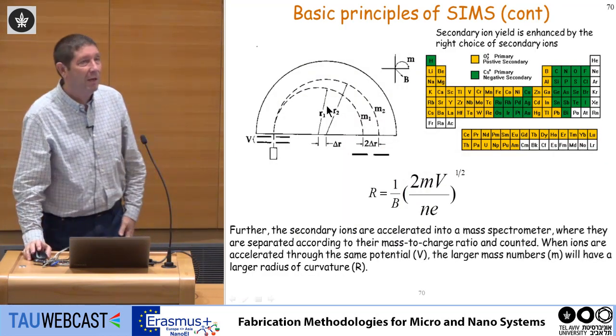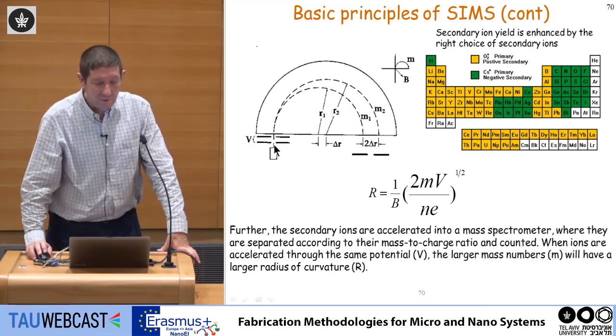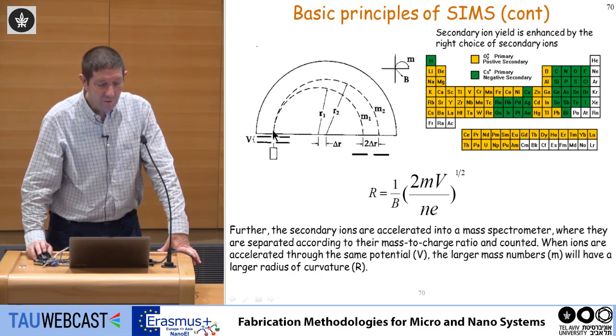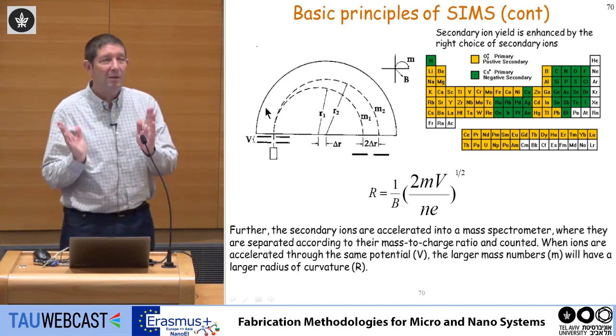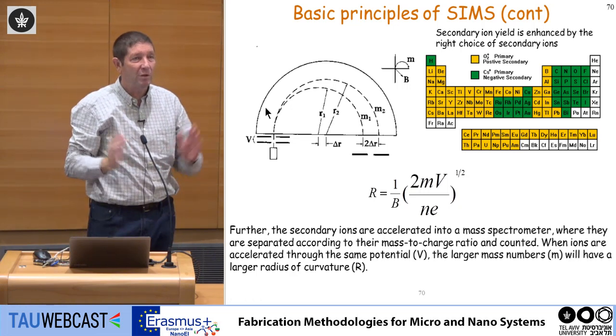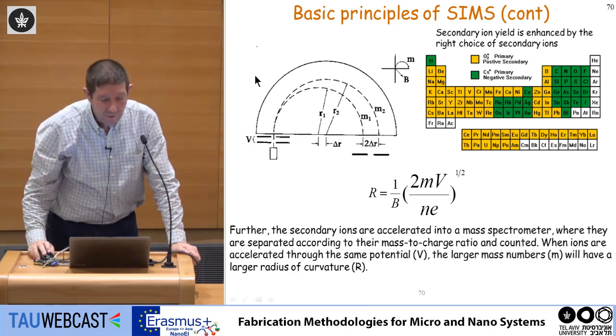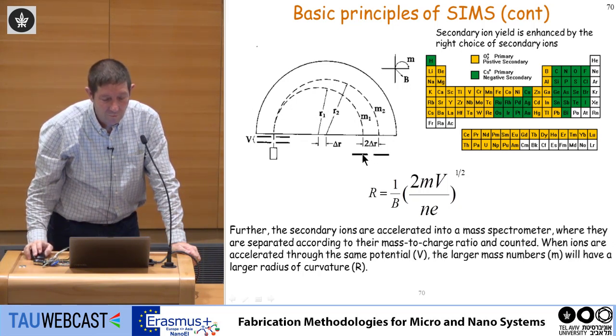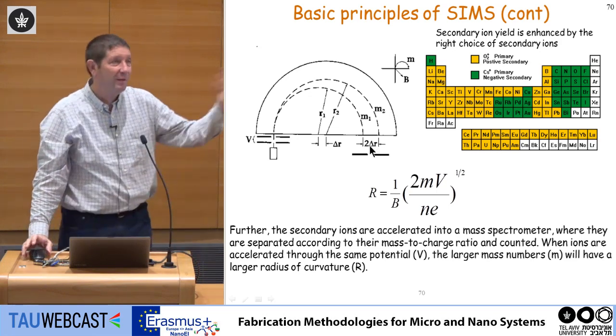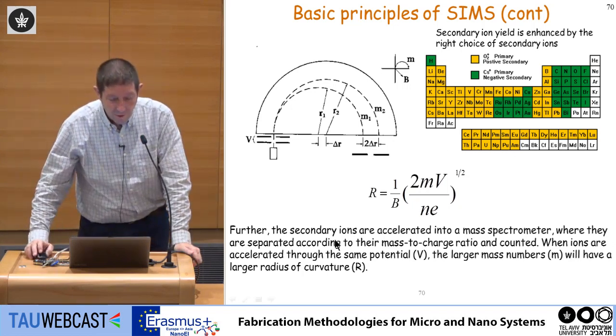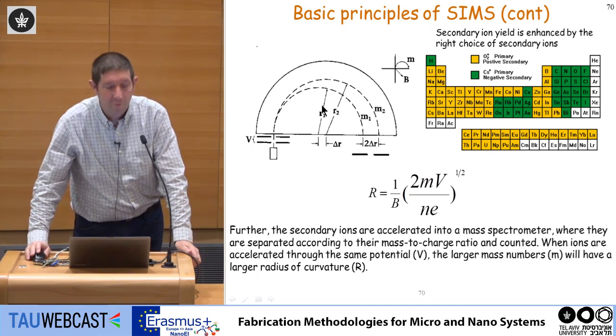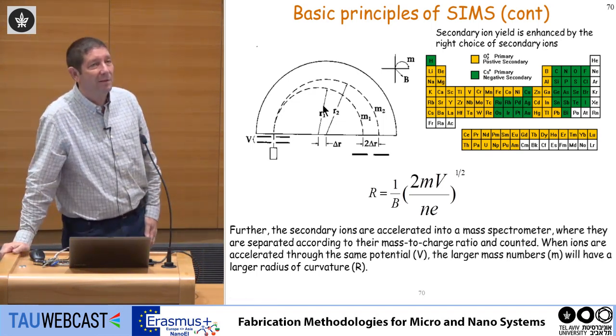Now, how to measure the secondary ions? There are two techniques. One of them is called magnetic deflection. If the ions are moving at a certain velocity, and I apply a certain magnetic field, they move in a circular motion because of the magnetic force, and the radius of this motion depends on the atomic mass. So I can put an aperture here. I can collect ions from here, ions from here, by just moving this aperture. This is the radius of curvature, and depending on the aperture, this delta R will define delta M, the difference in mass I can detect. The secondary ions are accelerated into a mass spectrometer. This is called a magnetic deflection mass spectrometer.